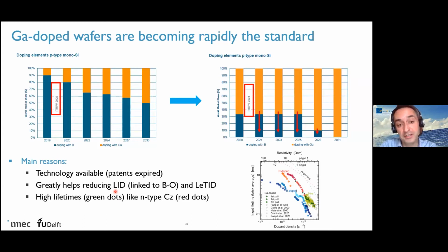If you replace the boron with gallium, you don't have this effect anymore. On top of that, people have become very skilled in making gallium doped wafers, and it turns out they also have higher minority carrier lifetimes than boron doped wafers, meaning gallium doped wafers are probably better suited to reach high efficiency devices.